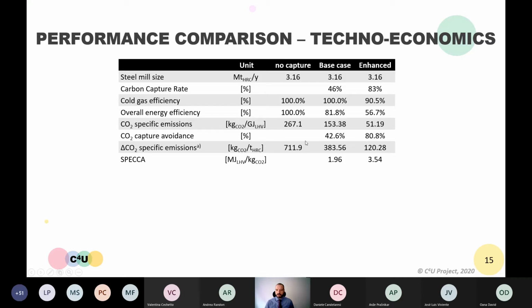Looking at the performance, what is worth mentioning here is that with respect to the case with no capture, the base case and the enhanced case will have a different overall energy efficiency. This is mostly due to the amount of CO2 that has to be captured, as well as different CO2 specific emission, which becomes much lower in the enhanced case. Higher CO2 separation will also result in a higher energy request per kilogram of CO2. And that's what you can see from the specific